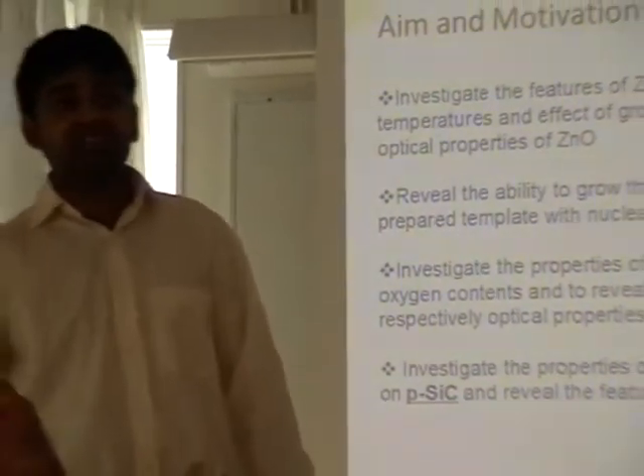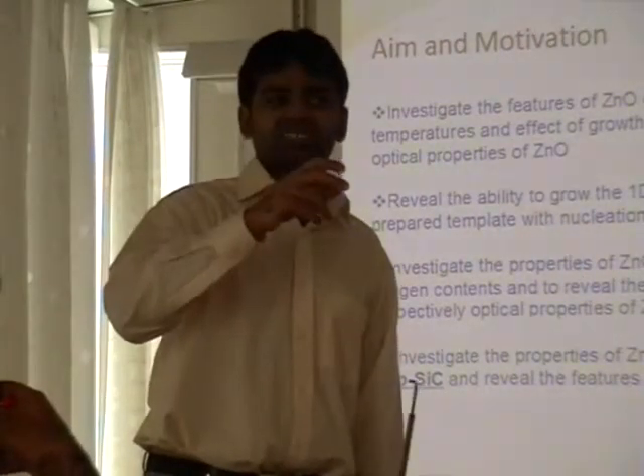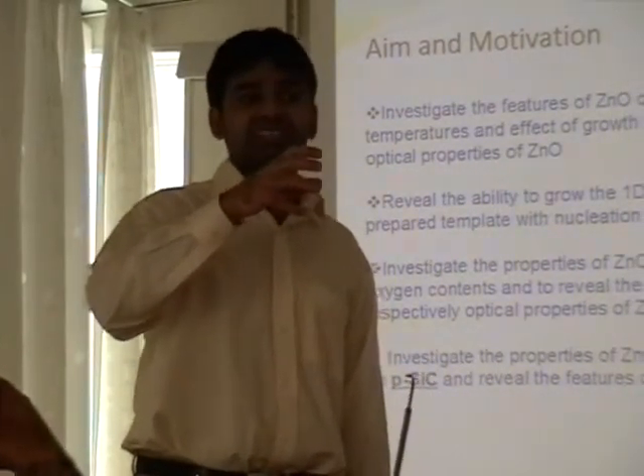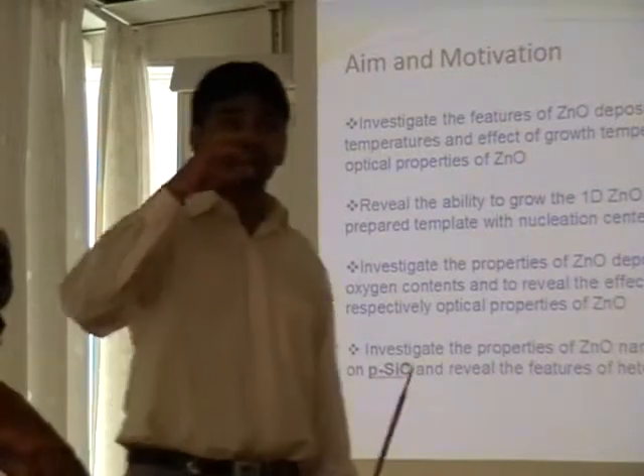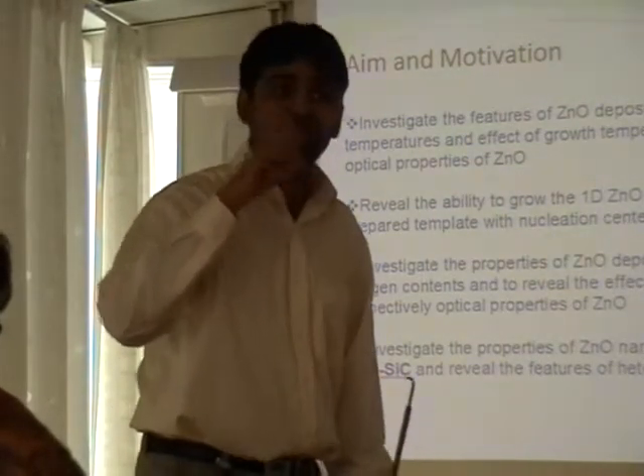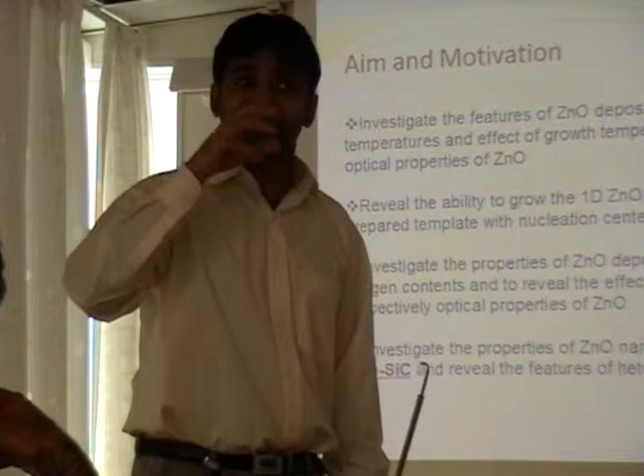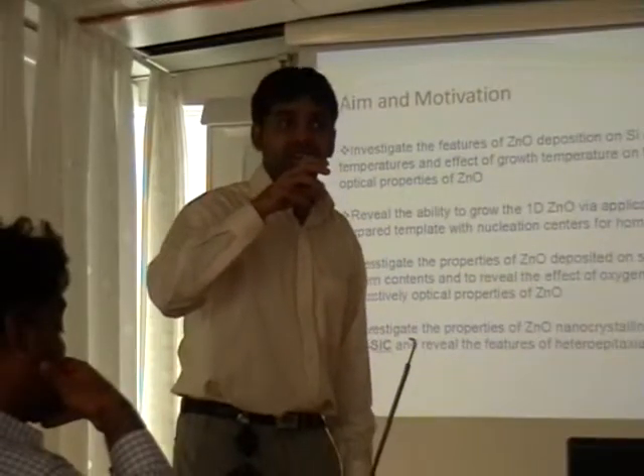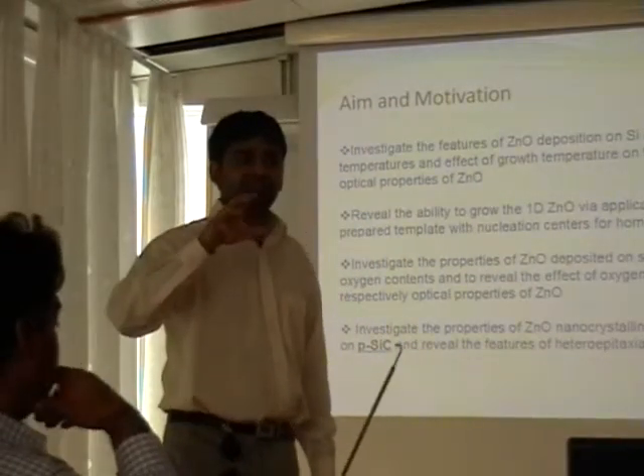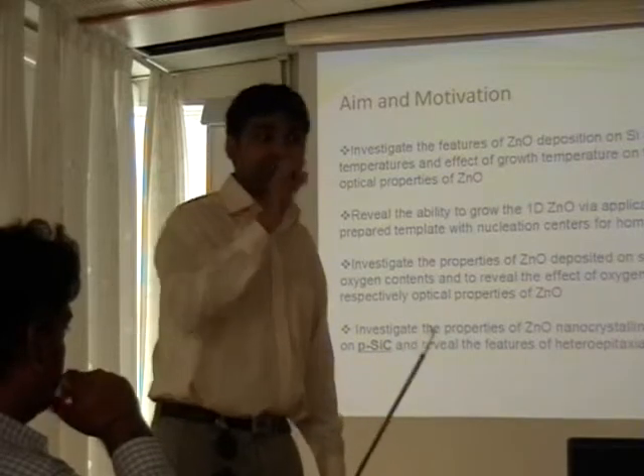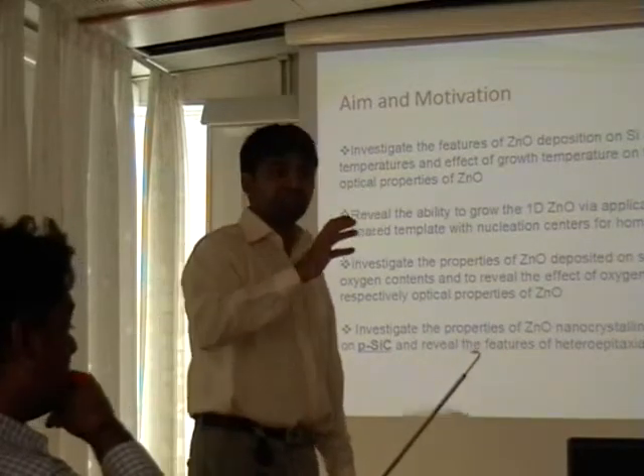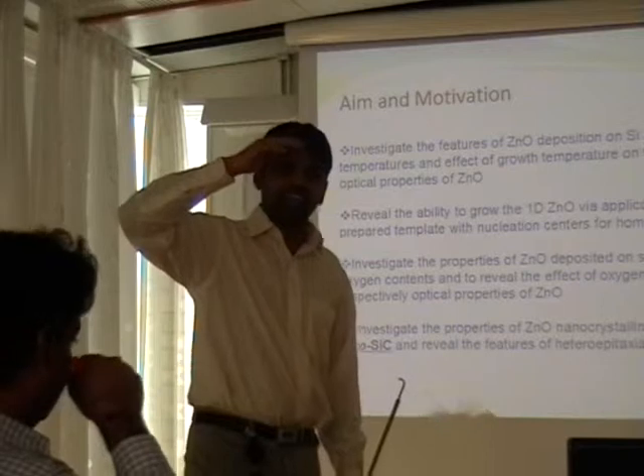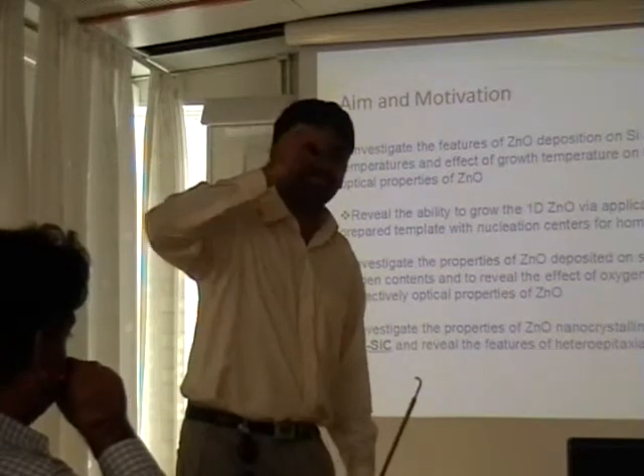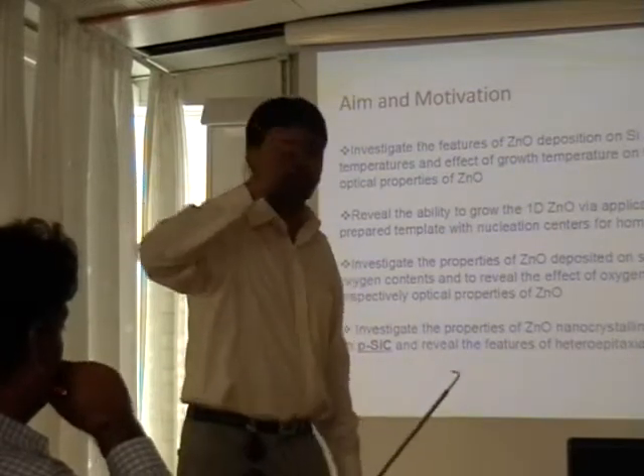The third thing: during the growth of zinc oxide or any growth technique, control of oxygen pressure in the chamber is a difficult task. Actually, it affects the structural and optical properties. We want to check how much effect there is whether oxygen is rich or oxygen is poor.